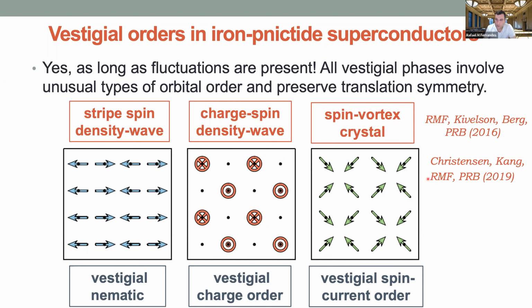But what I want to talk about is the vestigial order of this very unusual phase, which is the spin vortex crystal. It's a non-uniform, non-collinear phase where the spins form vortices around the plaquettes. And the vestigial phase is actually a spin current order.